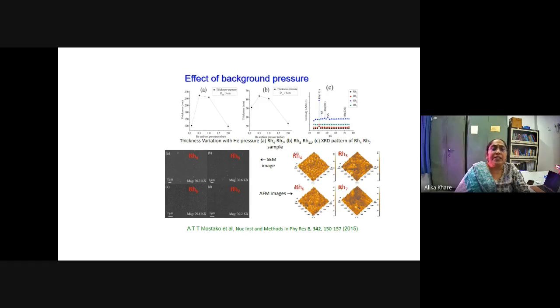When we increase the pressure to around 0.5 millibar, we got thickness around 270 nanometers. With further increase, the thickness fell down. The reason is that when it's freely expanding, the density of the plasma falls down, resulting in less thickness. When we slightly confine it, the density increases, so deposition increases and we get higher thickness. But beyond a certain optimum, the plasma becomes over-confined, and its size becomes smaller compared to the target-substrate distance, hence the thickness falls down.